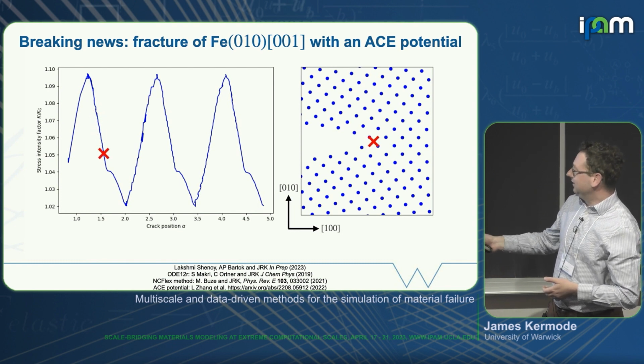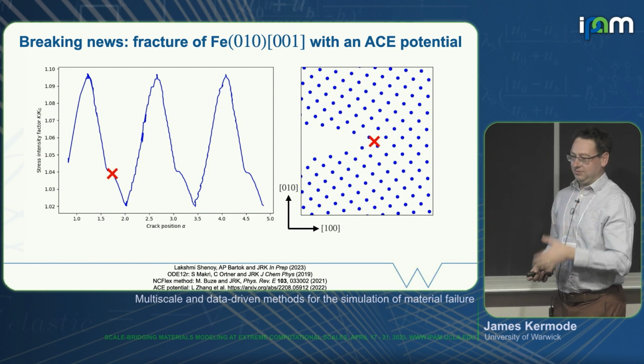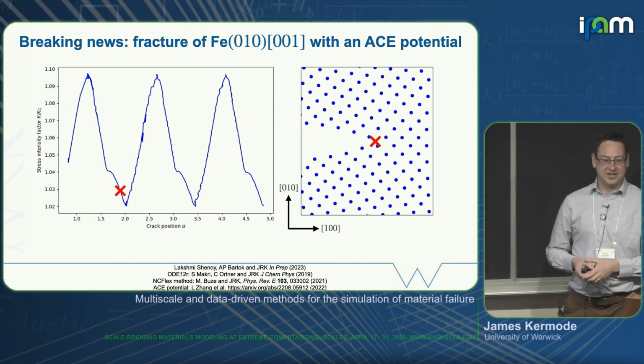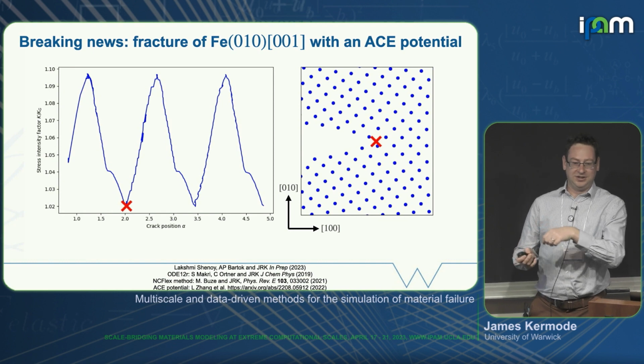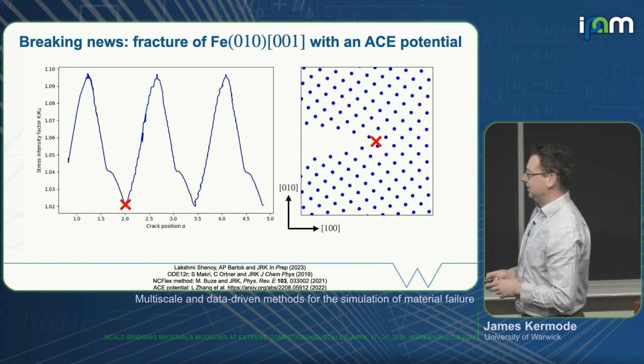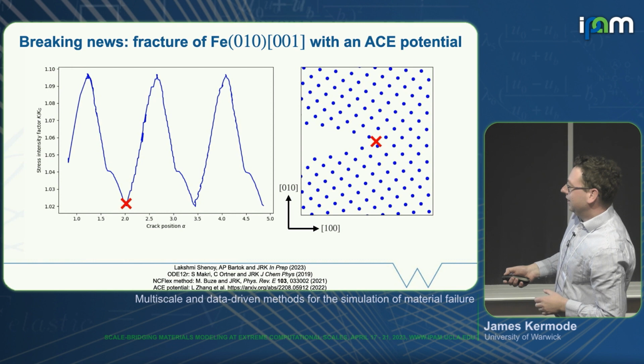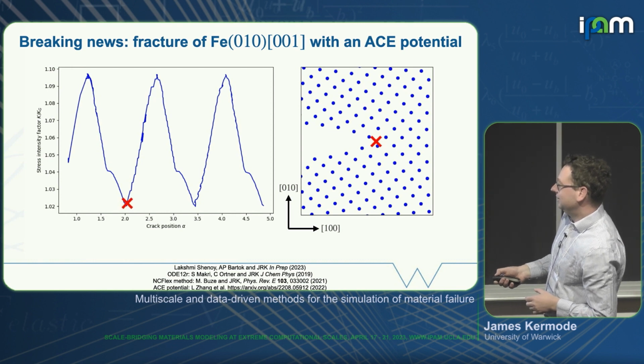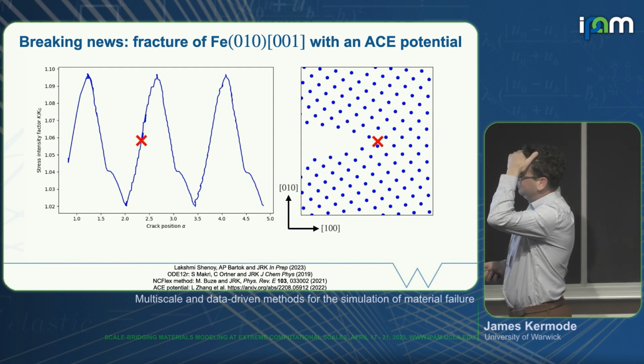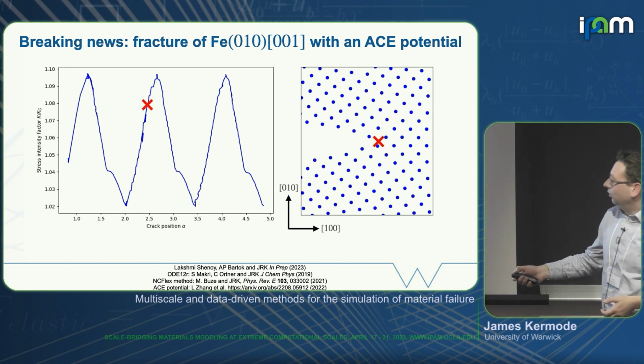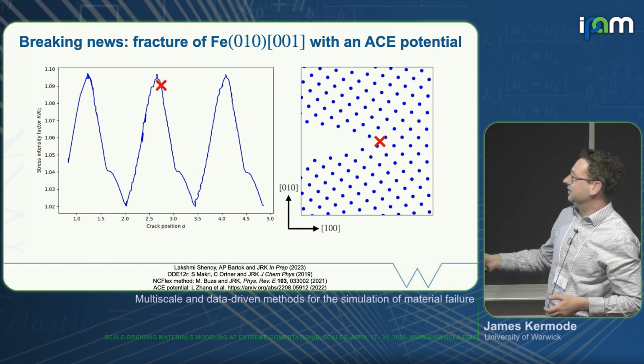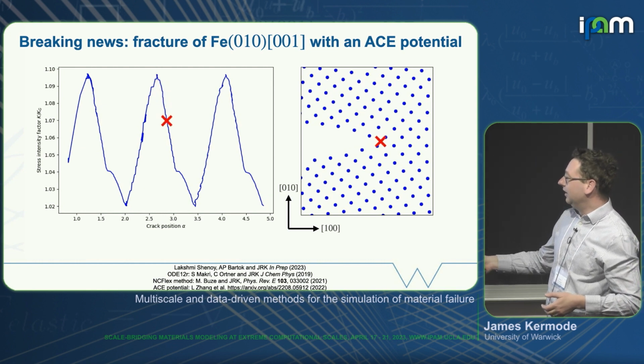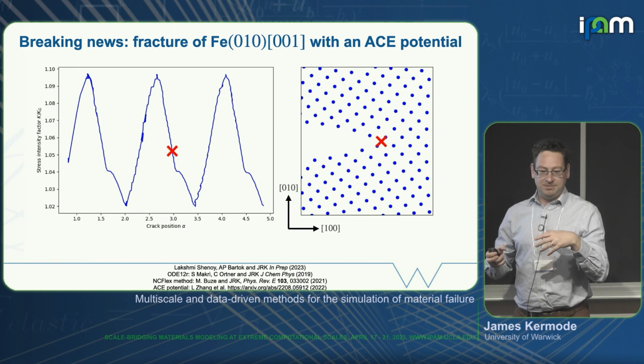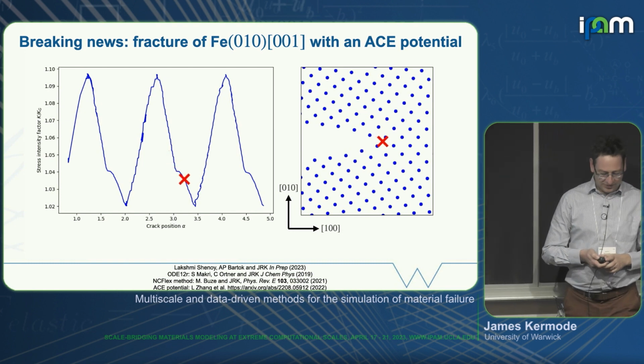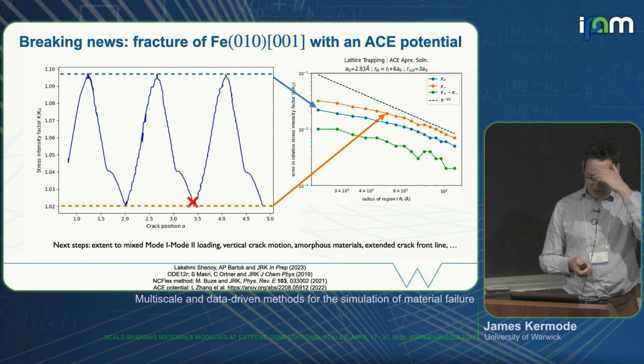We can see the crack advancing, with rather a sharper crack tip here, because of the metallic bonding associated with iron rather than the covalent bonding that we saw before, where bonds were more tightly defined. We're going round the loop. We're going to start jiggling along this next part of the diagram now. But the really appealing thing about this is that all of the subsequent crack advance steps are similar to one another, and that shows that our atomistic domain is big enough that we're capturing finite size effects pretty well. We can look at that a bit more carefully.